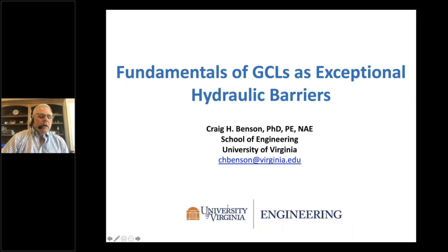Ahmed Alcoa: is it possible to use any other clays instead of bentonite that give higher performance? Not that I know of. The bentonites are really primarily montmorillonites. The montmorillonite is the special sauce, the active ingredient. It is the ability of the bentonite to swell when it hydrates that makes everything happen. That's the magic, all around the swelling of the bentonite. And you only get that because bentonite is montmorillonite rich, and that montmorillonite hydrates and swells.